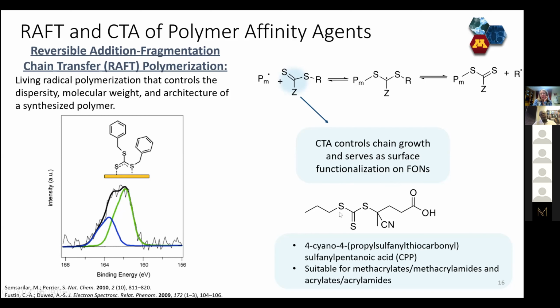And I'll say there was some strategy in choosing this chain transfer agent. If you notice, there's 3 sulfur groups in the chain transfer agent. We knew we wanted this molecule to stick onto gold, and there is a very high affinity between sulfur compounds and gold. And so this was a nice strategic choice to have that at the end of our polymer.